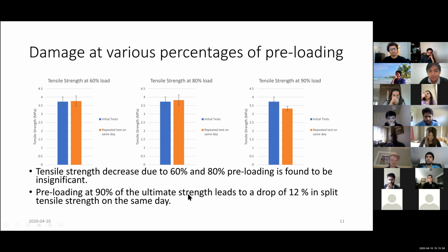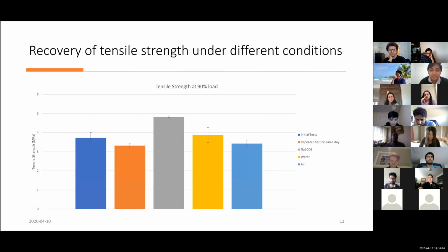But when I preloaded at 90% of the load, you can clearly see that there is a damage. It's about 12% of the damage, and it's on the same day if I repeat the test after doing it for once. And this is after healing. So the first bar is basically the initial test to quantify the strength. This is the repeated test on the same day. And this is the samples that were damaged up to 90% and then reloaded after 3 days of curing. And so they have a higher strength.